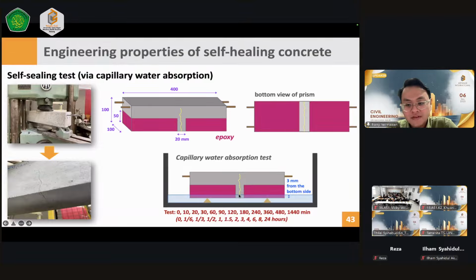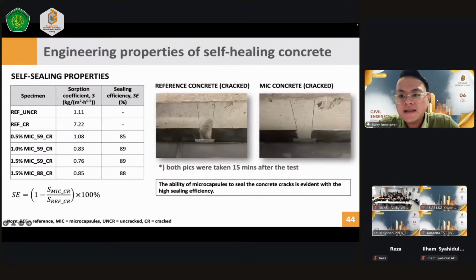I want to know how much or how fast the water can penetrate into the crack with this concrete type. If you look at the picture on the right-hand side, it's very interesting. From the picture on the left, on the reference concrete, when I submerged it and performed the capillary water absorption test, the water penetrates rapidly into the crack, and as you see, there was a wet area here. This represents that the water penetrates into the cracks and spreads all over the crack region. But with the MIC concrete, the concrete made of the microcapsules, you will see there were even no signs of water absorption or water penetration into the cracks.